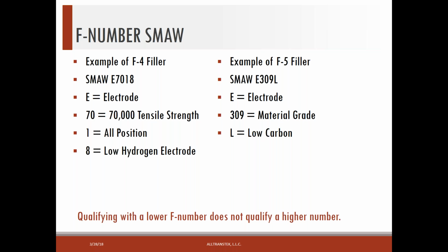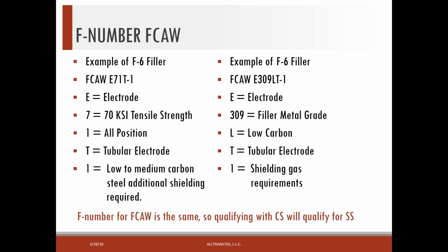And then like 309L, which is commonly used to weld carbon to stainless, it's an F5 filler metal. So if I qualify my welder on carbon steel 7018, he's not qualified to weld 309 because the F number is higher, which is kind of the exact opposite if I go to flux core, because flux core is an F6 filler metal, even if it's FCAW E71T1. So 7 is 70,000 tensile, 1 is all position, and T is a tubular electrode, and it's an F6.